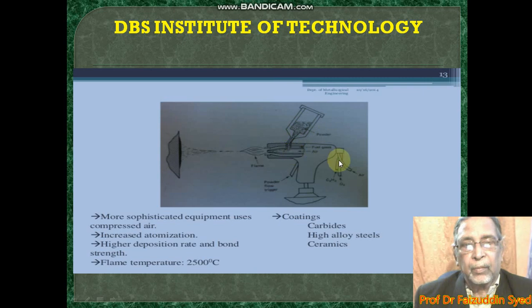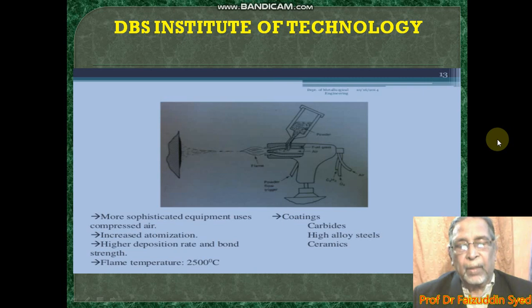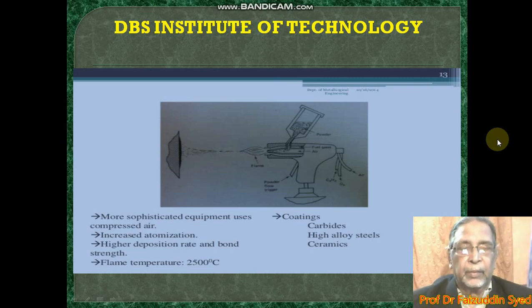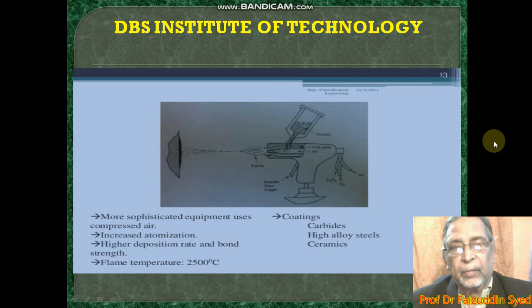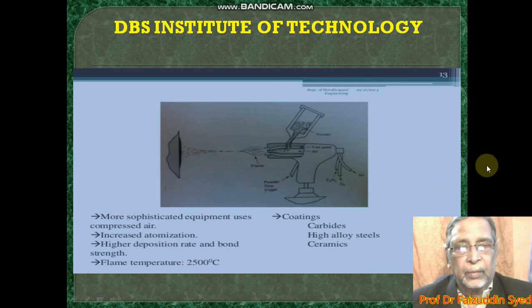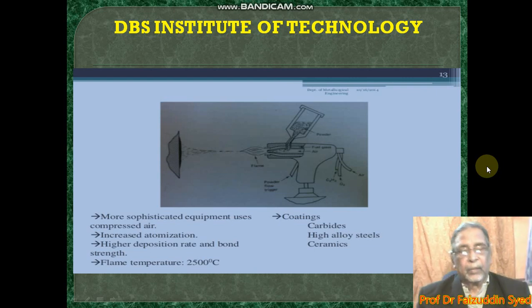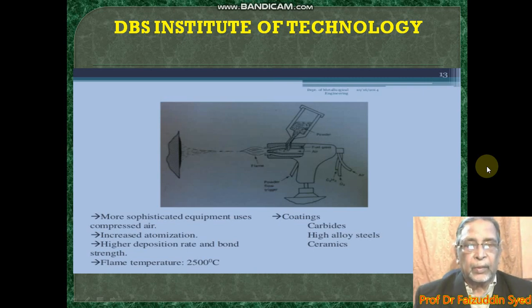At the back side you are seeing the hoses. From these hoses oxygen and acetylene gas will flow here, and it will give an acetylene flame. So how does this process work? It is more sophisticated equipment used with compressed air. You need compressed air to increase the atomization of the particles. You need higher deposition rate and bond strength. So in this process you will get higher deposition rates and bond strength. The flame temperature will be 2500 degrees centigrade.